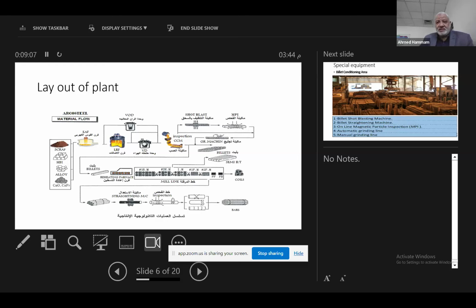After that, the final product goes to the straightening machine, to ensure that the bar is highly straightened according to standard, because it's going for a very dedicated application. Followed by the straightening, it should be inspected, getting results from the inspection by eddy current for the surface defects, and the internal defects by ultrasonic. According to that, every bar is released. And for special steel, the condition is that every bar should be tested by this. No bar is going out for special application unless inspected by the eddy current and the ultrasonic.